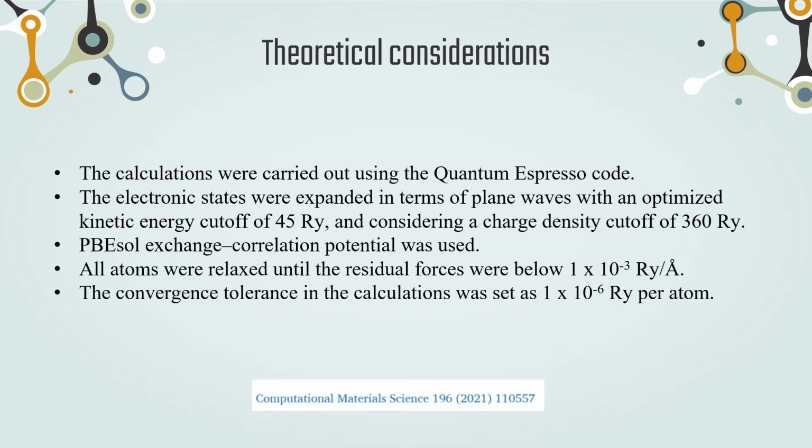Theoretical considerations. The calculations were carried out using the Quantum ESPRESSO code. The electronic states were expanded in terms of plane waves with an optimized kinetic energy cutoff of 45 Rydberg and considering a charge density cutoff of 360 Rydberg. The PBEsol exchange-correlation potential was used. All atoms were relaxed until the residual forces were below 1e-3 Rydberg per angstrom. The convergence tolerance in the calculation was set as 1e-6 Rydberg per atom. More detailed information can be found in this reference of our already published work.